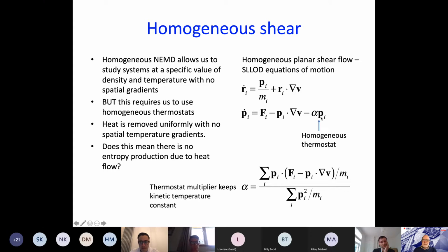In our homogeneous shear simulations, this is with the SLLOD algorithm, we have our equations of motion, where the second one includes the homogeneous thermostat. So we have our homogeneous thermostat, and that acts to keep the total kinetic temperature constant. But there are many other thermostats that we can apply. This is the standard kinetic thermostat that we use in non-equilibrium MD very often, but this is not the only thermostat that we can apply.